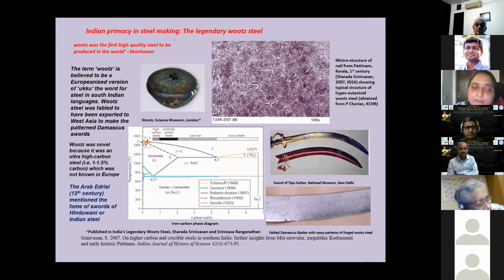Ultra high carbon steel is typically a steel with a composition of about 1 to 1.5% carbon. As you can see in that phase diagram, you get an idea of where that lies. Whereas wrought iron has very low carbon, less than about 0.4% carbon. And you also have these records of the Arabs in the 12th century, such as Edrisi, who mentions the fame of the swords of Hinduani, which is represented as Indian steel.